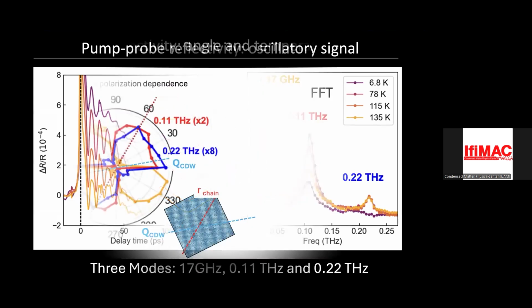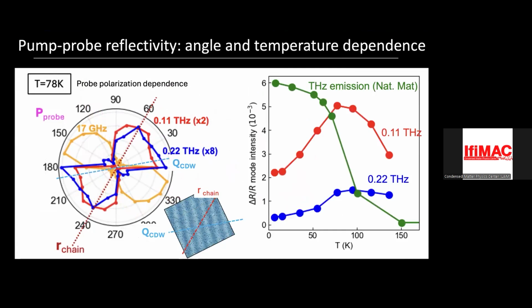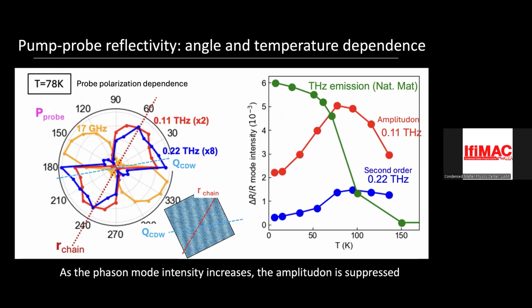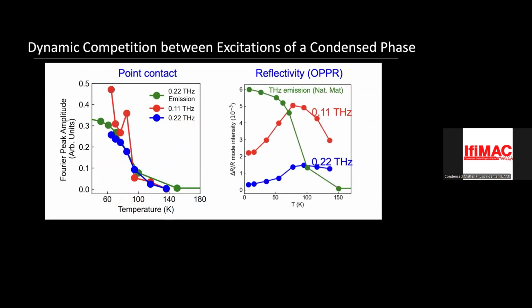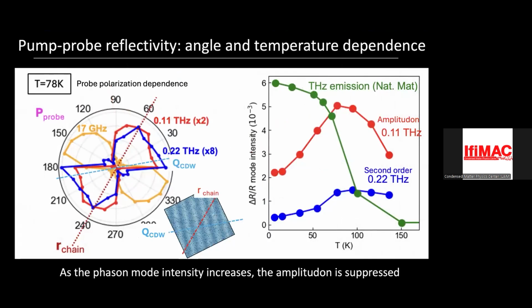Now we can look at the temperature dependence of this, and it's completely different. So this is the terahertz mode, which is what our 0.11 and 0.22 THz modes look like. This is the mode that reflectivity measures. And the question is, what is this and why does this intensity go down right when the intensity of this is going up? And the answer is, when you put everything together, it all makes sense. Essentially, as the 0.11 phason mode intensity increases, the amplitudon basically gets suppressed. That is the answer.